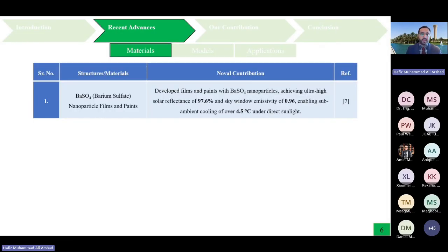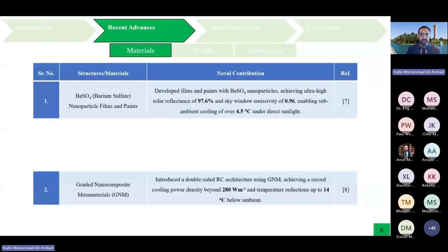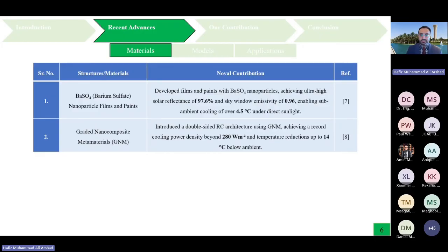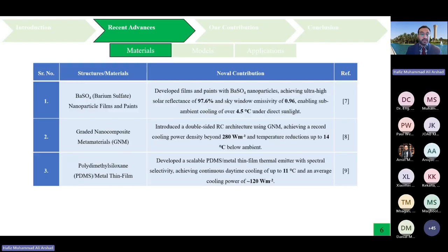Some of the materials, for example, barium sulfate nanoparticle films and paints, have been used in literature, and we were able to achieve radiative cooling under direct sunlight with a subambient temperature of 4.5 degrees C. And graded nanocomposite metamaterials were able to produce radiative cooling up to a subambient temperature of 14 degrees C. Then PDMS with a combination of metal thin film has the ability to produce radiative cooling during daytime, subambient temperature up to 11 degrees C, and with a cooling power of up to 120 watt per meter square.